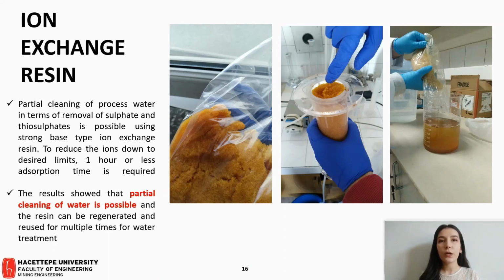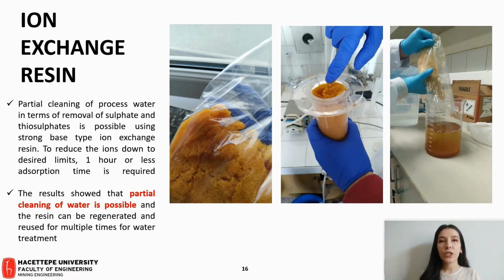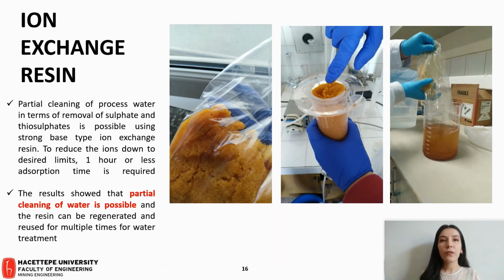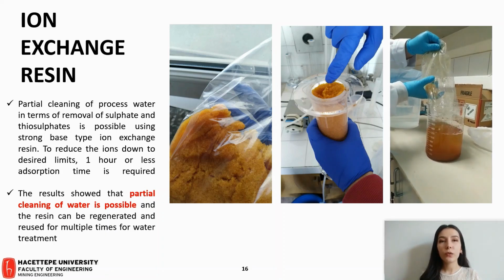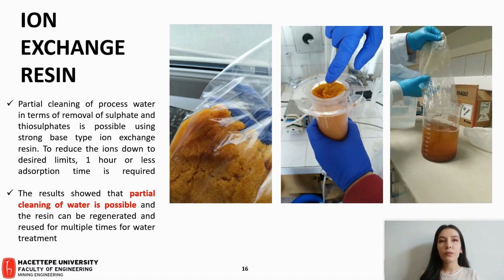To reduce the ions down to desired limits, 1 hour or less adsorption time is required. In adsorption, 84% of sulfate in water could be successfully removed. Regeneration of the ion exchange resin was also performed, and it was found that the resin could be used multiple times for next water treatment stages.